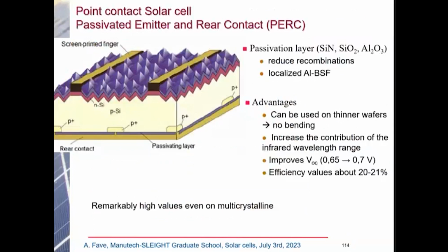So the new technology that is the standard one now is what we call the passivated emitter and rear contact. What does it mean? What is the difference from the previous one? It's here on the back side. You can see that there is a layer between aluminum and silicon. This is a passivating layer that can be silicon nitride, silicon oxide, or alumina. This layer will passivate the surface, so reducing the possibility of recombinations. It can act also as a mirror to reflect the light, to improve the possibility for infrared light to be absorbed into the silicon.